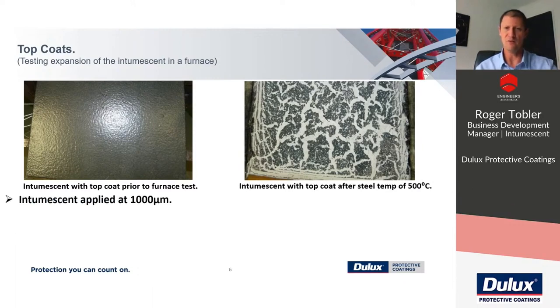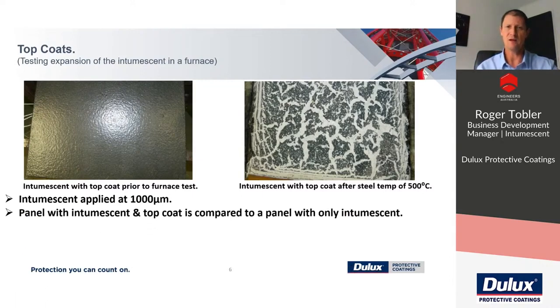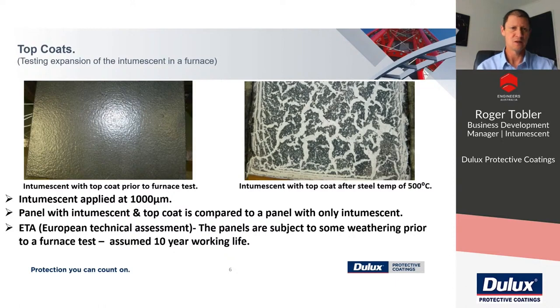So now an evaluation is done, and the evaluation is both a visual inspection and a comparison to a panel that wasn't top coated. The requirement is that the panel with the top coat performs at least to 85% of the panel without the top coat. This is a test that's described in a European technical assessment. The panels are subject to a small amount of weathering before this, then the furnace test, and this European technical assessment then states that there's an assumed working life for that system of 10 years.